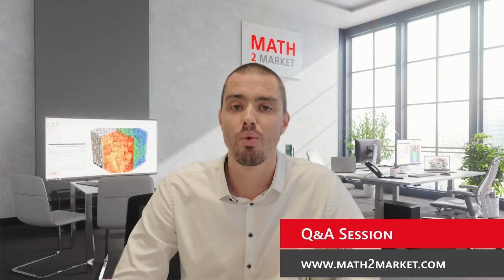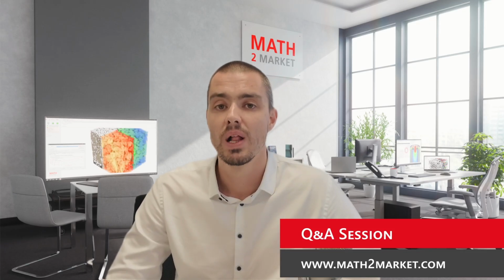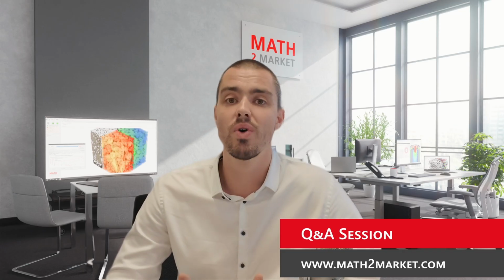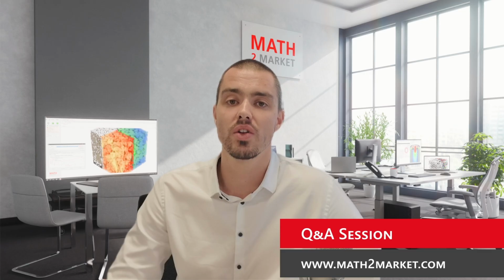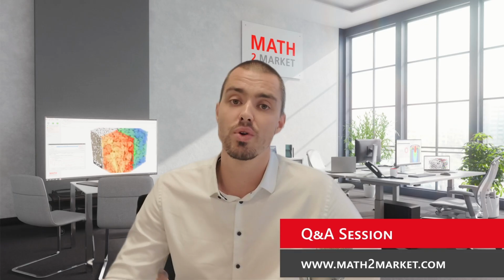So in this example that I have shown, what I basically did was trying to generate a tight or more tight subsample, not considering any particular properties. In general, the most valid approach would be to have the subdomain imaged, for example, with nano-CT or FIB-SEM imaging at much higher detail, where you can then segment and directly predict the properties on that model.